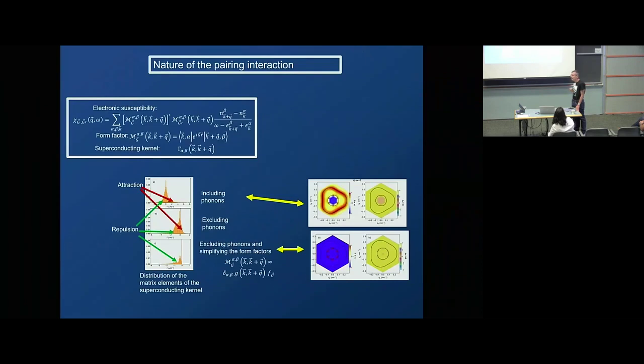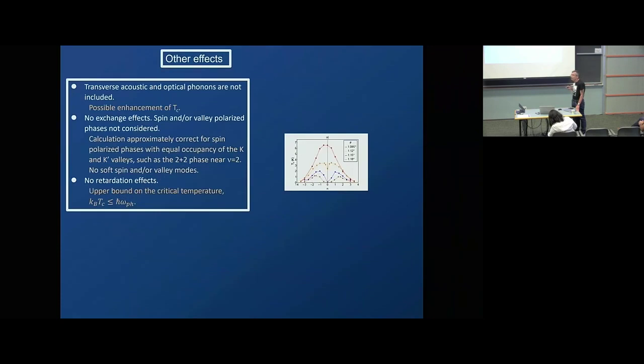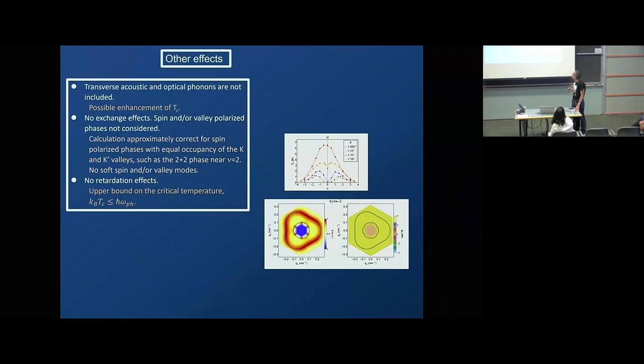At the end of the day, I repeat, for TBG we get F-wave superconductivity with a full gap in each pocket. There are things we miss, because for instance we use the static dielectric function due to computational limitations, so that puts limits on the validity of these results. We cannot go to high temperatures because then things like the frequency dependence of the screening will be important, and there are no retardation effects. And we don't have other types of phonons, for instance optical phonons or TA transverse acoustic phonons. But the results for this kind of coupling through charge fluctuations only are pretty robust, and you get definitely superconductivity.